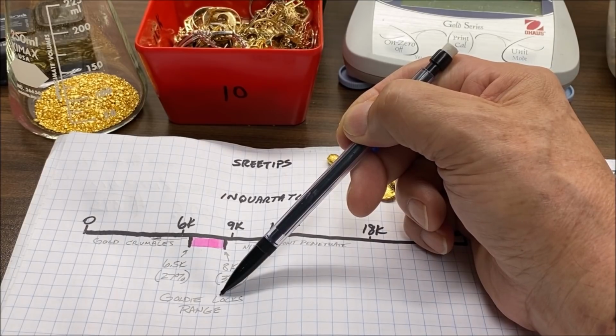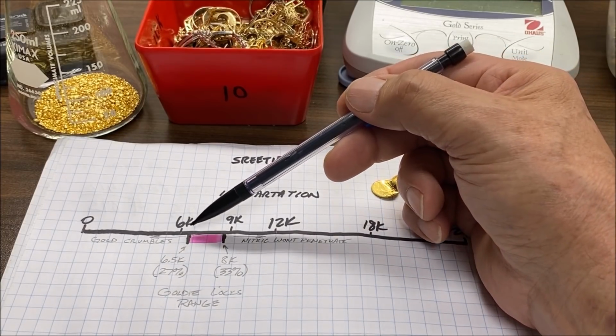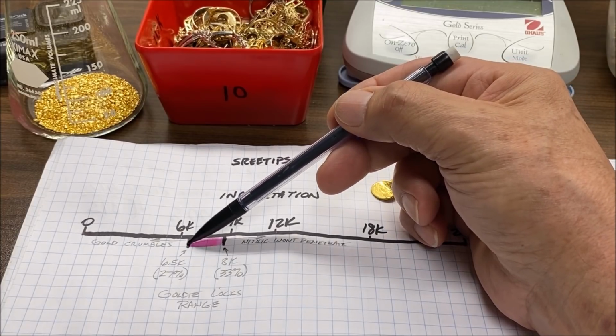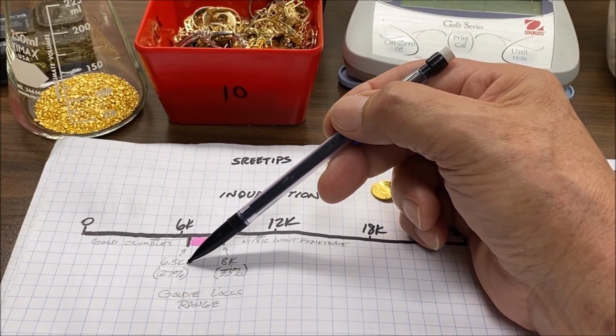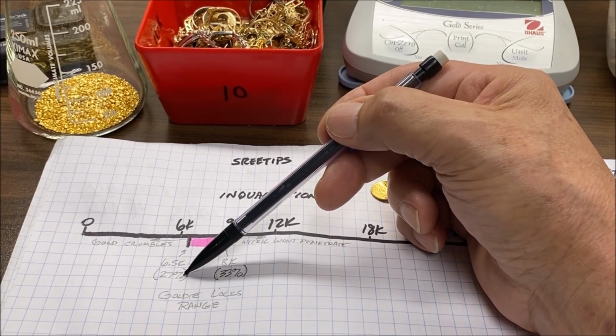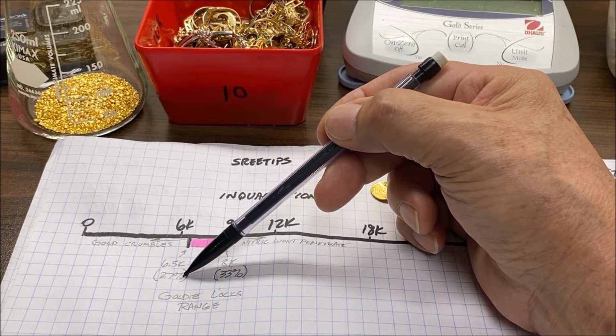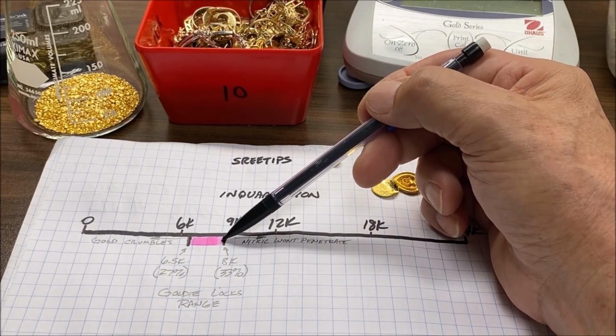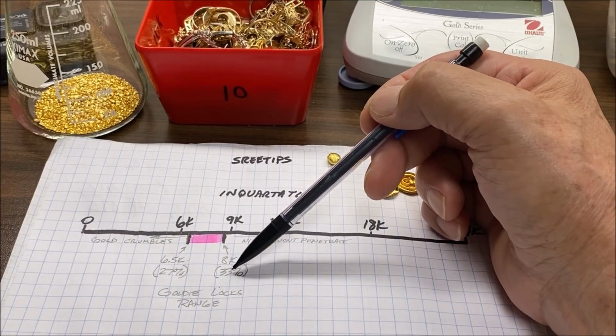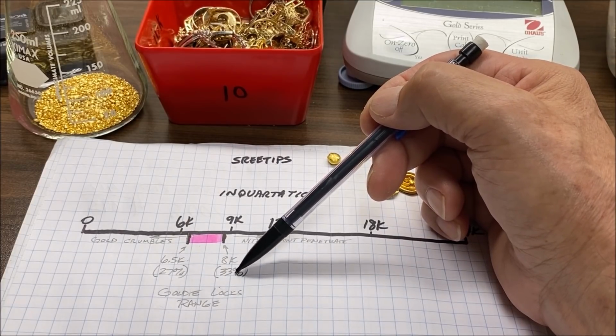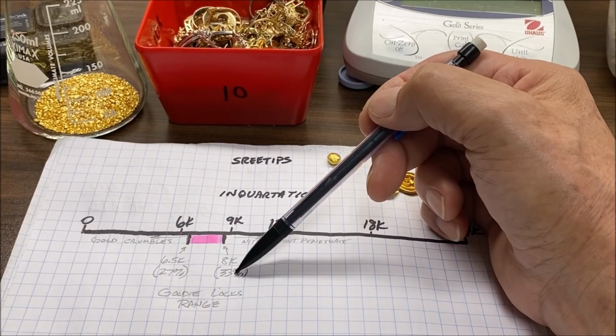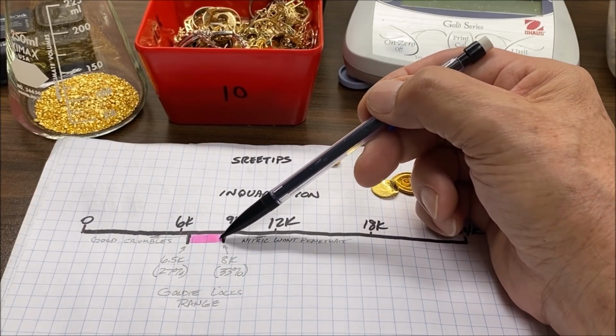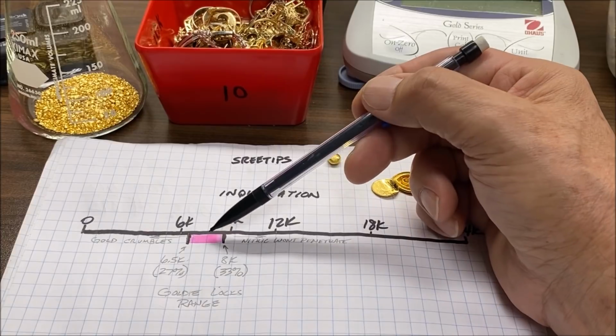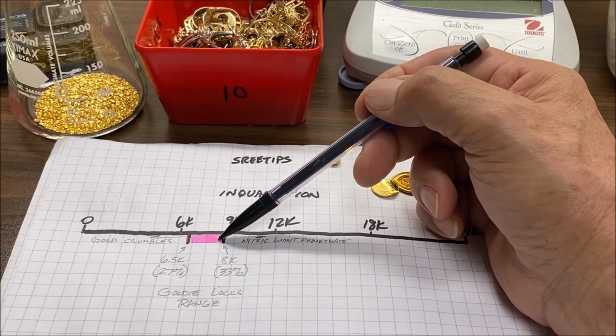In my experience, I've found that when I inquart the gold, there is a Goldilocks range that we want to stay inside. And what I've found is an alloy that makes 6.5K, or about 27% pure gold for the low range, all the way up to 8K, or 33% pure gold alloy. This area right in here will give the best result when we go to do the nitric acid boils.